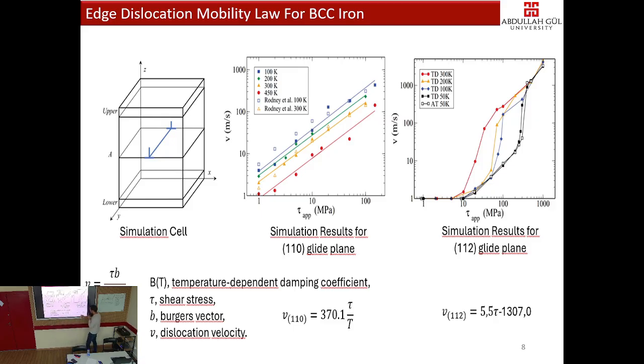And the velocity law for 112 plane is not a function of temperature, but just shear stress. But we will focus on both planes, but the most important equation output is here. In literature, the mobility law is only τb/B, and the drag coefficient is only a function of temperature. What happens if we have hydrogen?